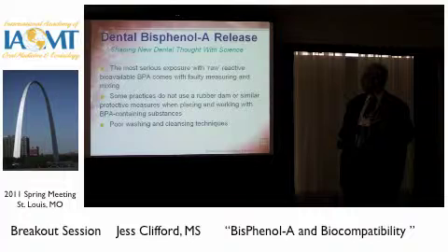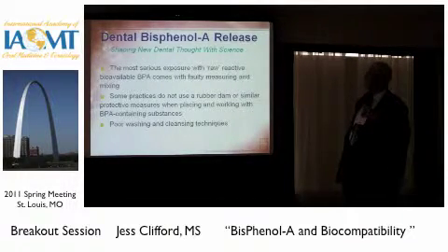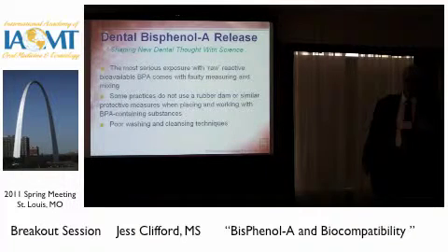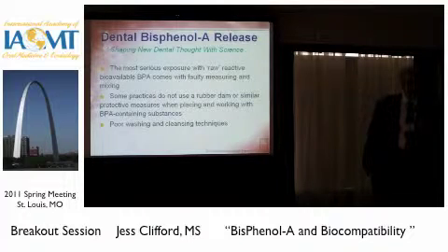The most serious exposure from raw reactive bioavailable material comes with faulty measuring and mixing. Today, auto mix cartridges have saved the bacon for a lot of us. But if it says mix 1 part A and 1 part B, that doesn't mean 9/10 part A and 1.1 part B. But sometimes when things get in a hurry and we manually mix, what do we end up with? One of those components is in excess. It may or may not allow proper polymerization in any of the mix that is there, and you end up with something that's going to stream bisphenol in an irregular way for a while to come, as in several days' worth. Care in mixing. This is a matter of care in your practice.